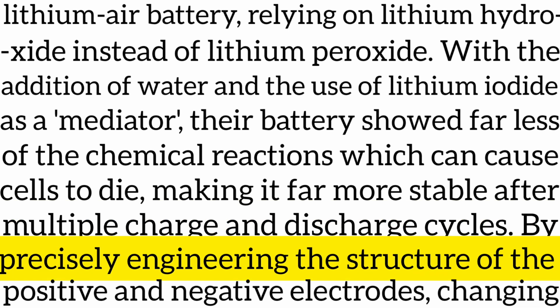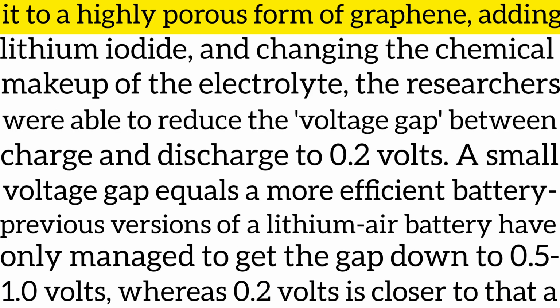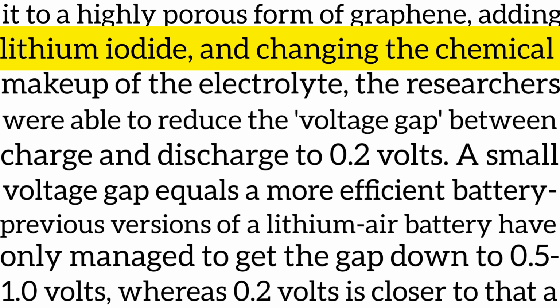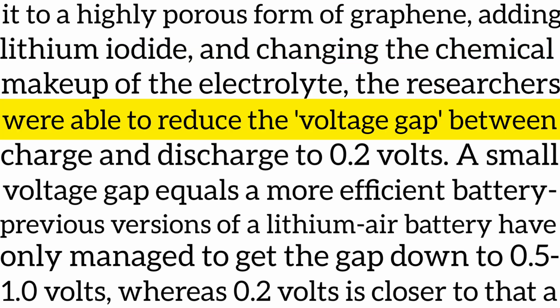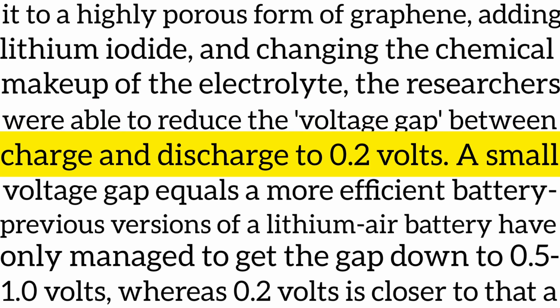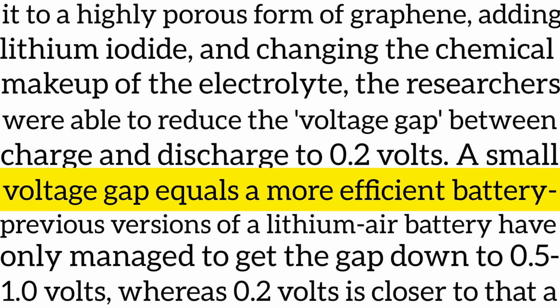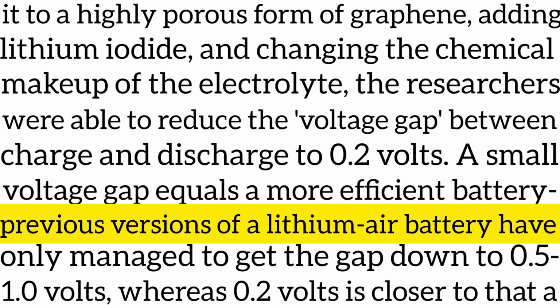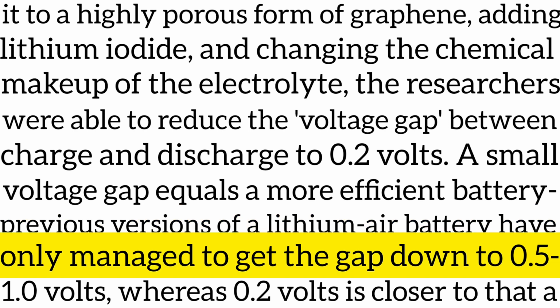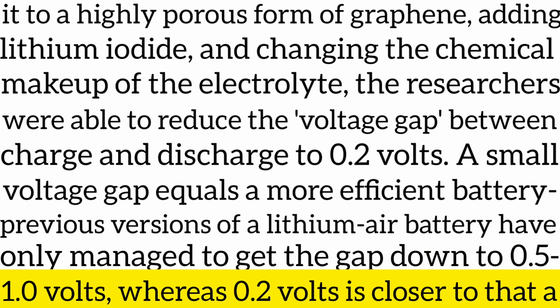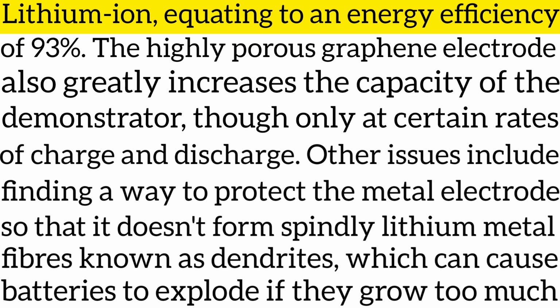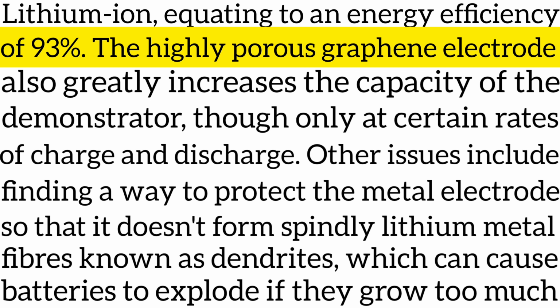By precisely engineering the structure of the positive and negative electrodes, changing it to a highly porous form of graphene, adding lithium iodide, and changing the chemical makeup of the electrolyte, the researchers were able to reduce the voltage gap between charge and discharge to 0.2 volts. A small voltage gap equals a more efficient battery. Previous versions of a lithium air battery have only managed to get the gap down to 0.5 to 1.0 volts, whereas 0.2 volts is closer to that of lithium ion, equating to an energy efficiency of 93%.